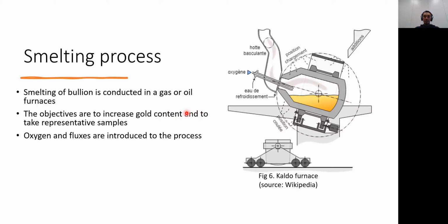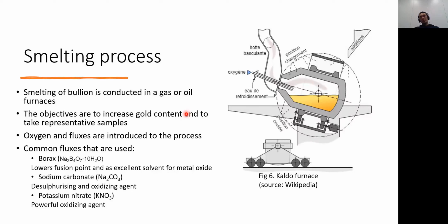In the metallurgical view, oxygen and fluxes are introduced in the process to oxidize all the impurities, mainly base metals. The common fluxes that are used are borax, or sodium borate, with this chemical formula. The borax lowers the fusion point of the metal oxide. I think Professor Taskinen and Dr. Imam know this better than me. And then also sodium carbonate as a desulfurizing and oxidizing agent, and potassium nitrate as a powerful oxidizing agent. But bear in mind that potassium nitrate must be used quite cautiously, because it is quite dangerous.